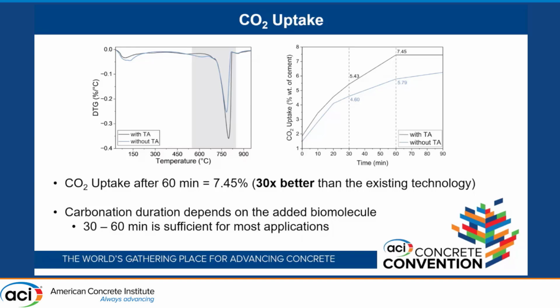Compare that to the 0.2% weight of cement that I mentioned earlier, and you get something that is nearly 30 times better than any existing technology. And keep in mind, this is only for about 30 to 60 minutes of carbonation, depending on which biomolecule you use and how much of that biomolecule you use.